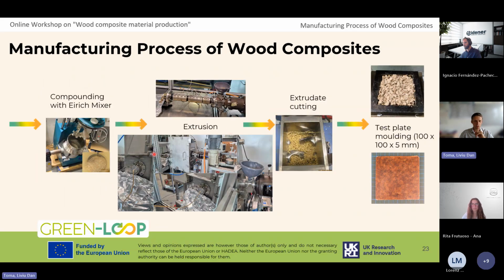Basically, we chose to compound the mixtures in an Eirich mixer. Then we perform the extrusion using a classical extrusion unit where the barrel is electrically heated, or using microwave-supported heating. A few words more about this in the next slides.